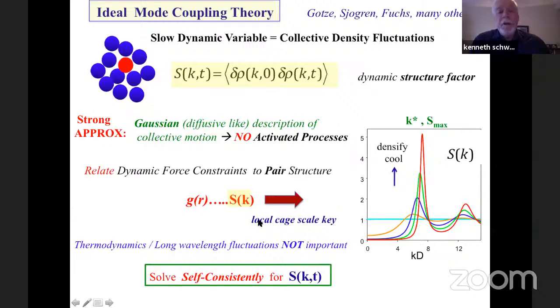And in mode coupling theory, although there are more advanced versions of it, generally one views the most important part of the structure as the local structure. Now, in this approach, long wavelength fluctuations, which are in the structure factor and are related to thermodynamics, are not playing an important role, at least as far as I understand. So then you can self-consistently solve for the dynamic structure factor, and this work has now been around for over 3 decades and has been tremendously valuable.